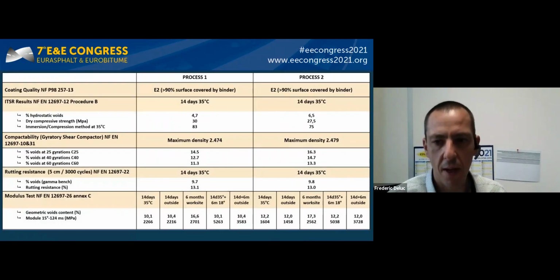On this slide, we have summarized the performance results of the two processes. In terms of coating, more than 90% of the surface of the aggregate is coated by the asphalt. In the case of water susceptibility, it can be seen the two processes are virtually identical. For compactability, both processes provide void contents which comply with the specification in the current French standard for emulsion mixes,